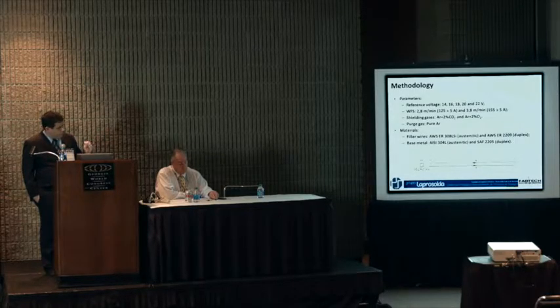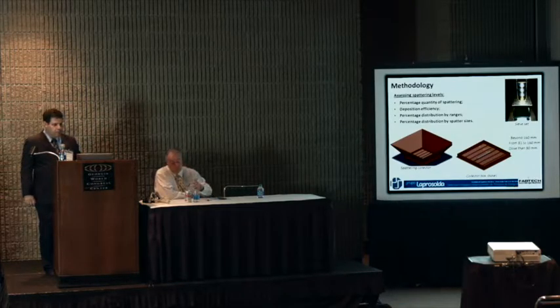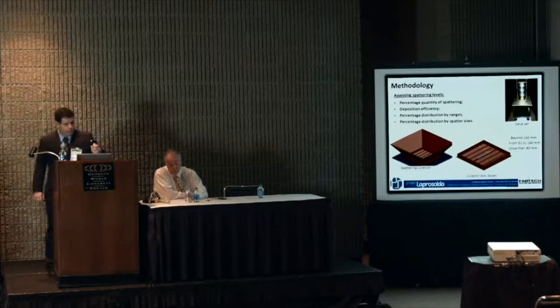The weld metal that we use is a small stainless steel bar, 3/8 of an inch, 10 millimeters, and 200 millimeters of length. So the idea is to deposit the weld pool only on that small bar, so we can collect all the spattering. I'll show you in a moment. Okay, how can we do that?